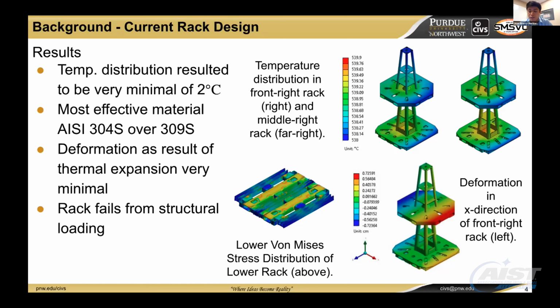That deformation is in the X direction, and it's very minimal, not enough to cause failure. It was also found that the most effective material is AISI 304 stainless steel. And the main conclusion was that the rack fails from structural loading. As you can see in the bottom left image, you can see the stress distribution in the forklift channels.